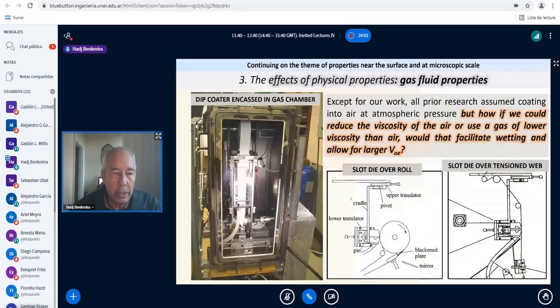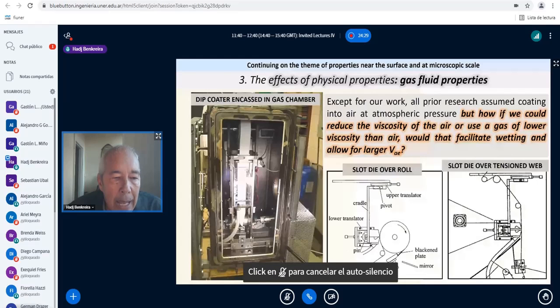So what we did, we took our coater, as you see, and we encased it in a gas chamber. And in this gas chamber, we could change the atmosphere. We could put air, we could put CO2, we could put helium. And furthermore, we also decreased the pressure. And we decreased the pressure to such an extent that we could affect the viscosity of the gas. So we went as low as 10 millibar.